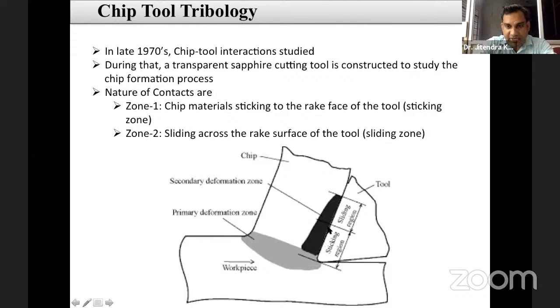But after some time, this sticking changes to sliding. Due to that change from the sticking to the sliding zone, some material is removed from the tool surface, because the material is cold welded over the surface. Now if you want to move that material over the same surface, then some material can be detached from that surface. So that's why the crater wear you have seen on the rake surface happens, because of that reason.